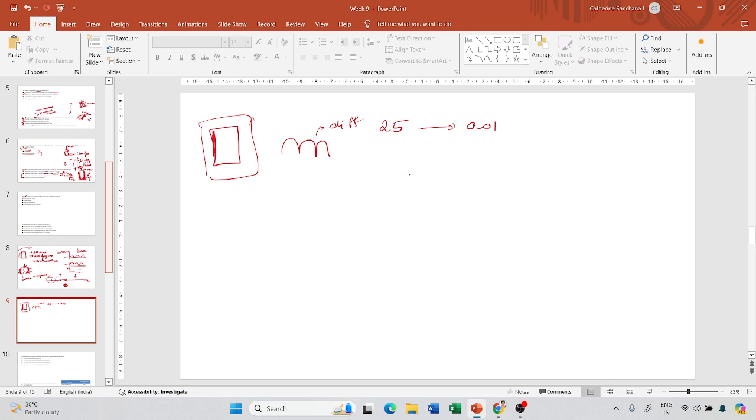This is for one sample. Now if you're planning to do all the temperatures on the same sample, you should always start from the lowest temperature to the highest temperature. This is for temperature and this is for frequency.